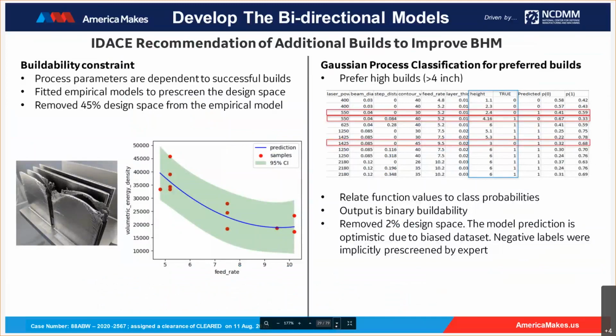One interesting observation during the additive build, and actually it's not just for this project, is a well-known challenge: not all the builds will be successful. That's the buildability constraint we have been facing. So in order to improve the buildability or feasibility of the additive builds, we introduced two sets of classification models to evaluate the process parameters and to improve the buildability. The first buildability constraint is the empirical fitting between the mass feed rate and the volumetric energy density for the existing builds. We have collected about 13 successful builds, shown as the red dots in the figure, and the green region is an indication of the domain with a high chance of success. All the points falling outside this green domain are deemed to have less chance to be successfully built.